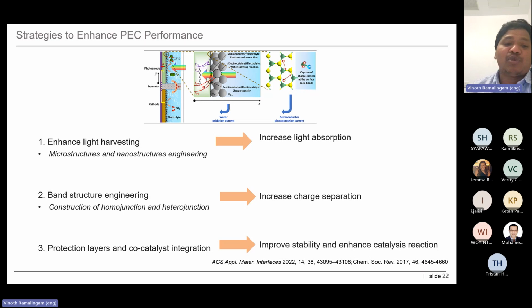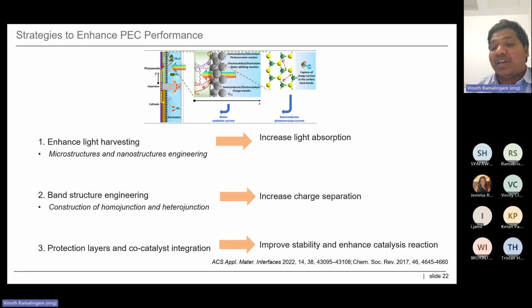Again, the protection layer is really important to avoid photocorrosion or the degradation of the photoelectrode during the water splitting reaction. The other one is co-catalyst integration, that will really help you to enhance the catalysis reaction on the surface of the photoelectrode, because most of the photoelectrodes are very good photo absorbers, but really poor catalysts. In that case, we need a co-catalyst. A co-catalyst is nothing but an electrocatalyst, which we can directly use with the photoelectrode to drive the reaction. So I'll just go through one by one with some examples.